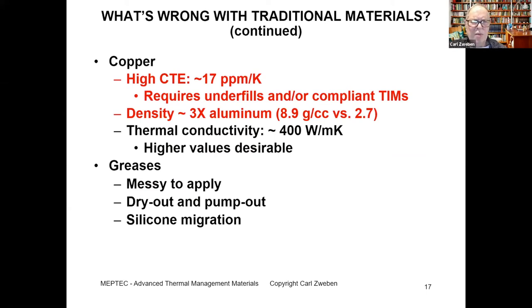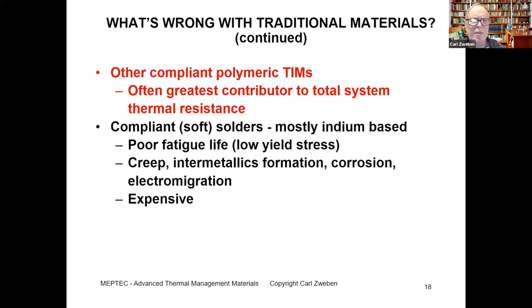It's got a good thermal conductivity, 400 watts per meter Kelvin, but again, we would like higher values if we can get them. And as you'll see, we can with advanced materials. So if we look at the various TIMs, thermal interface materials that we use, starting with greases, they are messy to apply. They're subject to dry out and pump out, and also silicone migration.